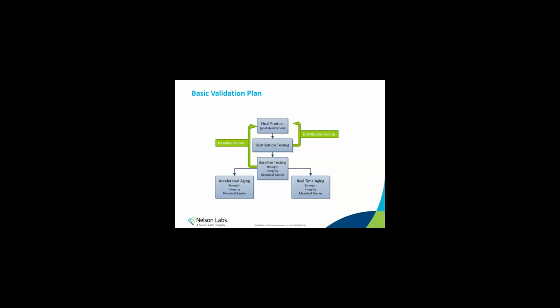The aging time points are chosen by you and based on what you want your label claim to be. You must test baseline or time 0 and the final time point. But sometimes people include an interim time point as an insurance policy in case something unexpected happens at the final time point. Validation costs increase with longer final time points and with additional interim time points. After aging is completed, you repeat the same testing that was done on baseline for strength, integrity, and microbial barrier. And if you meet the acceptance criteria in your protocol, then you've proven that the sterile barrier system remains intact and effective through the expected expiration date.